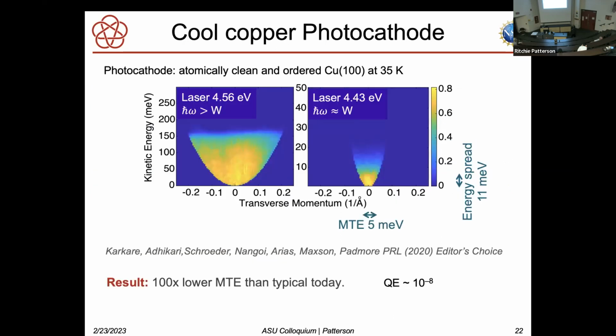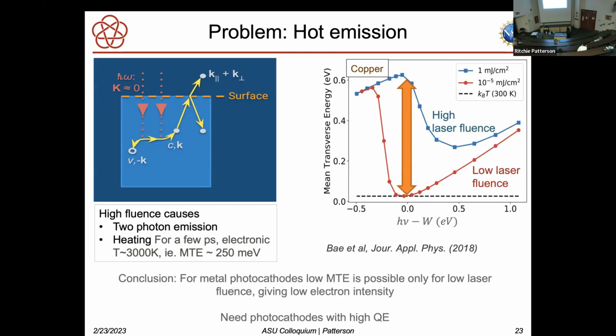So you might say, why not hit it with a lot of laser light, get out a lot of photoelectrons? Who cares if there's a low quantum efficiency? The reason that's not a good idea is that you have a large photon flux. A single electron can absorb multiple photons, and therefore you get high kinetic energy electrons coming out. And you can see that in this theoretical prediction here.